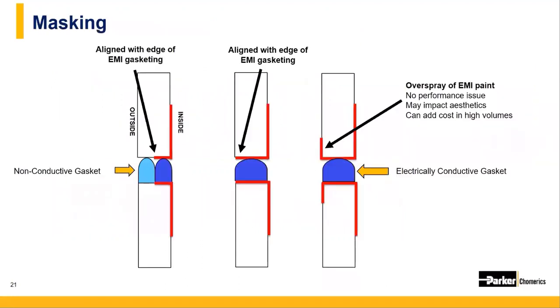Masking is another important step when you're applying these conductive coatings onto your housing. We just want to briefly mention the importance of making sure that the paint is applied to all the edges that will come in contact with your EMI gasket or other conductive surfaces. So using a non-conductive gasket mated up against a conductive paint will defeat the whole purpose of the coating and open up your design to EMI susceptibility.